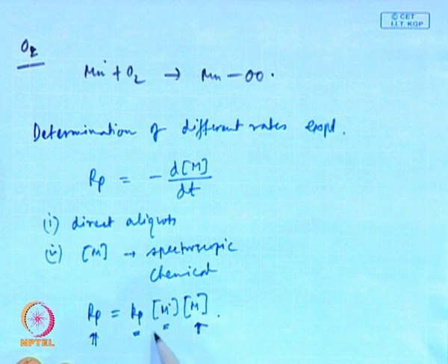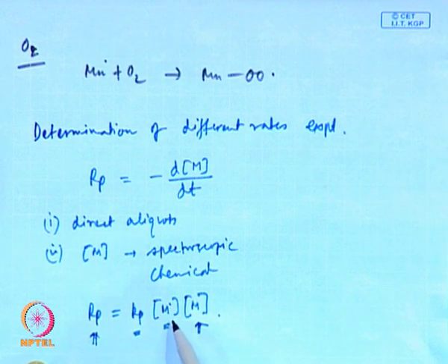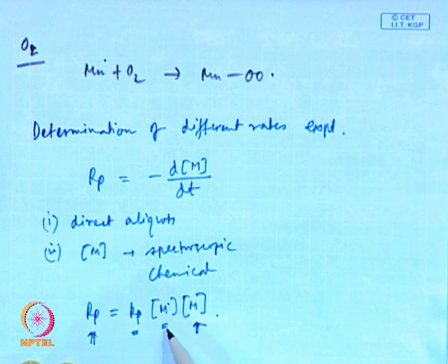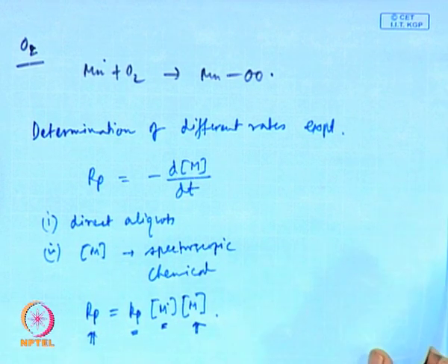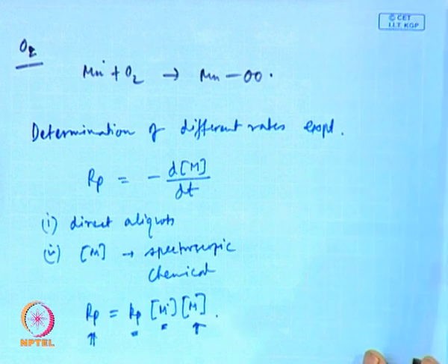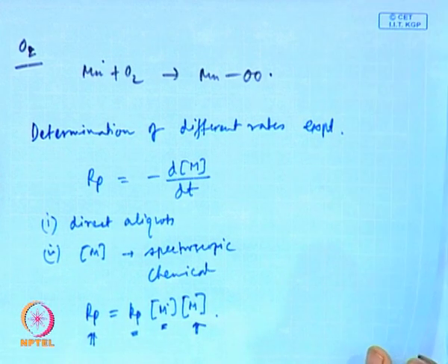Now, M dot, in principle, can be found directly from ESR measurements, which can give the total radical concentration at the steady state. But because the lifetime of these radicals is very small, normal ESR technique is not very accurate in finding the value of M dot.